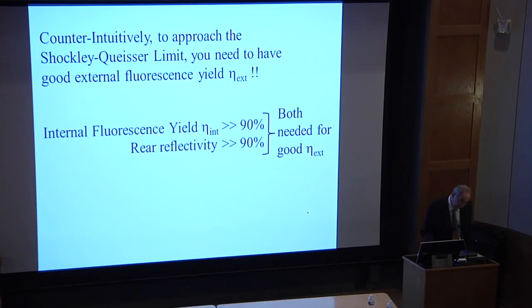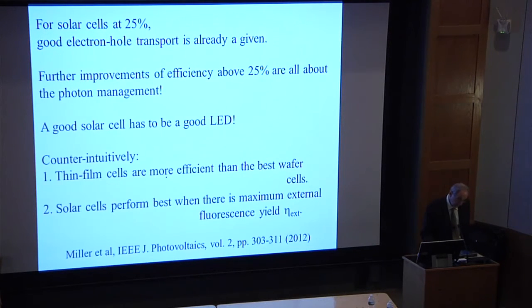So there are two things you need to approach the world record, and one of them is you need a good material, so good internal luminescence yield, well over 90%, and you also need well over 90% for the mirror. And both of these are needed to achieve a record solar cell.